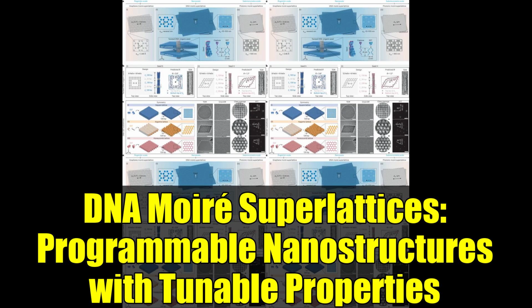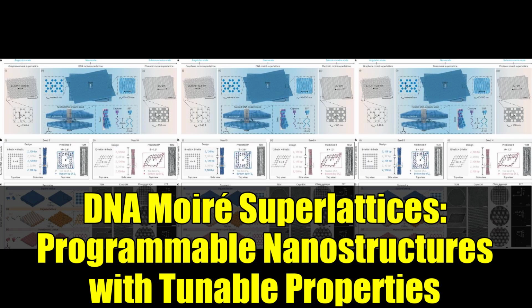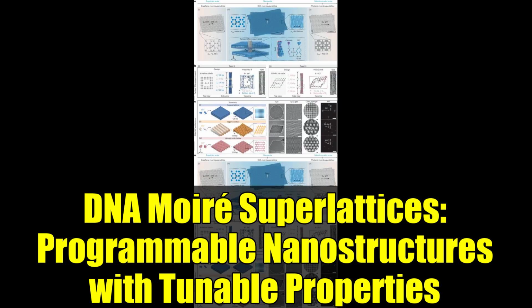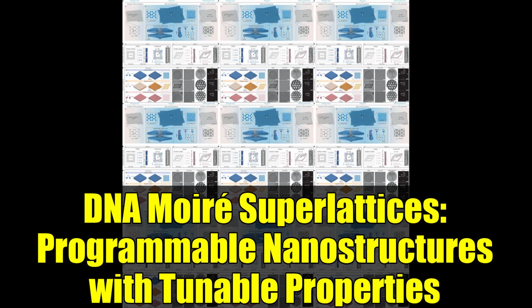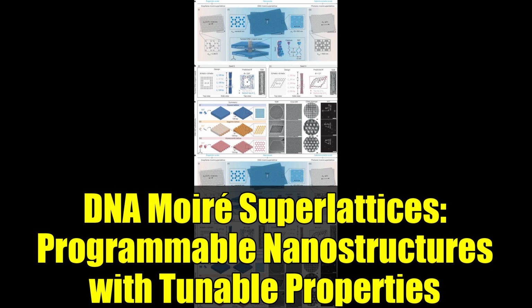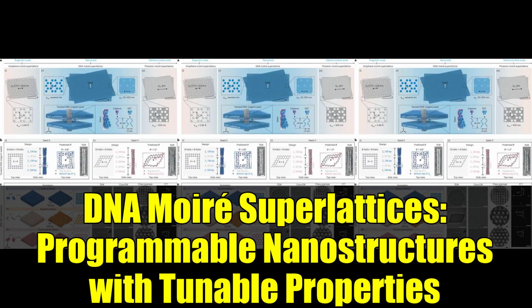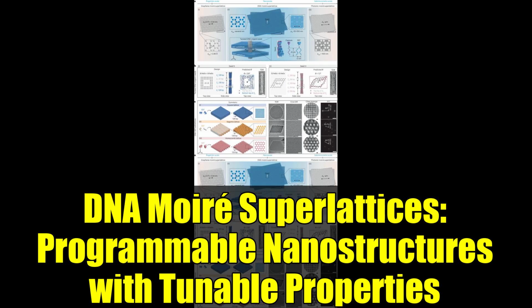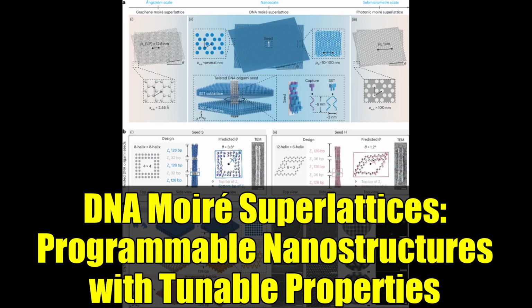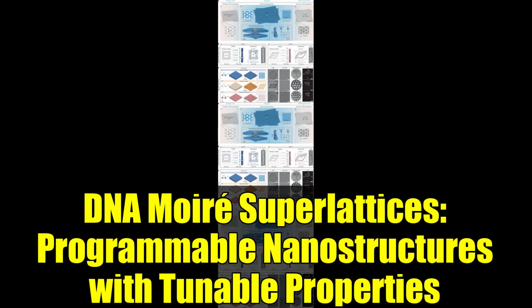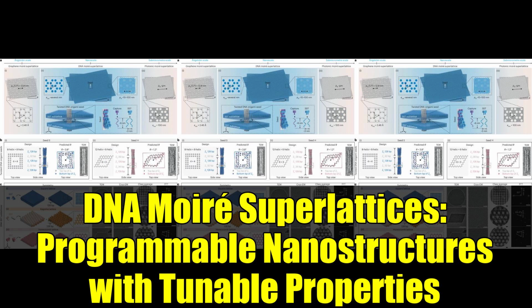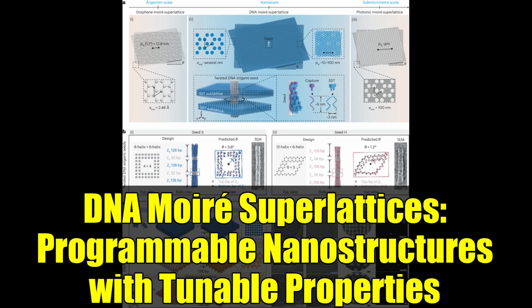Now, let's clarify for beginners. DNA origami is a technique where long strands of DNA, combined with many short staple strands, fold into specific 2D or 3D shapes, much like paper origami, only billions of times smaller. In this work, engineers created two types of hollow DNA bundles, called seed S and seed H, with precisely controlled geometries and internal twist angles. These seeds feature distinct regions for starting and growing DNA layers, but crucially, they include special segments like Z2 and Z4 that precisely set the twist between layers, controlling the resulting Moiré pattern.